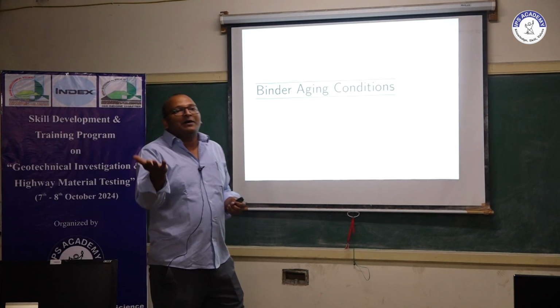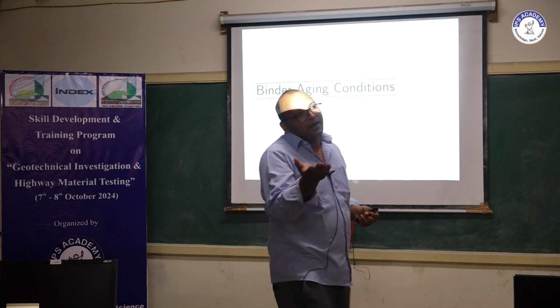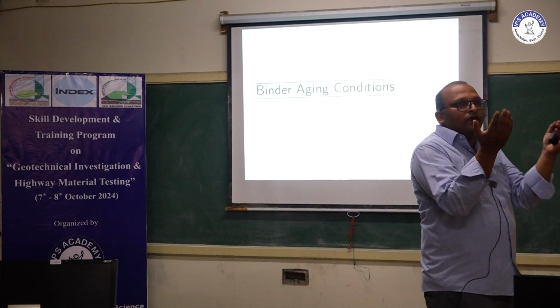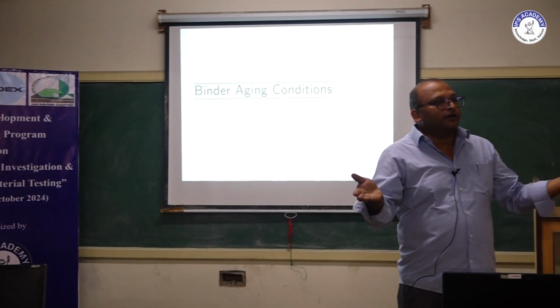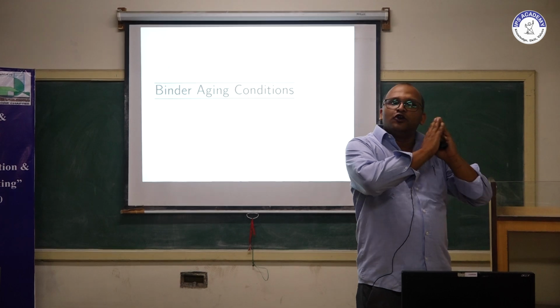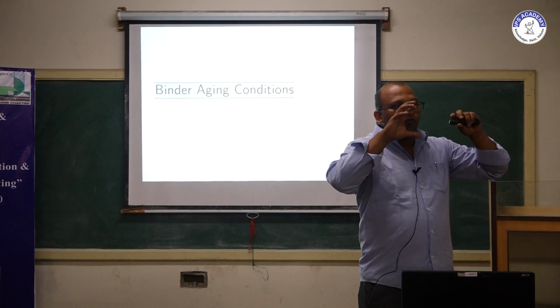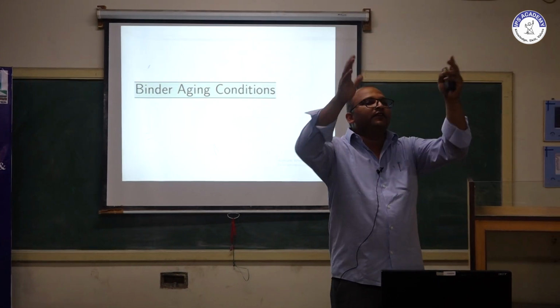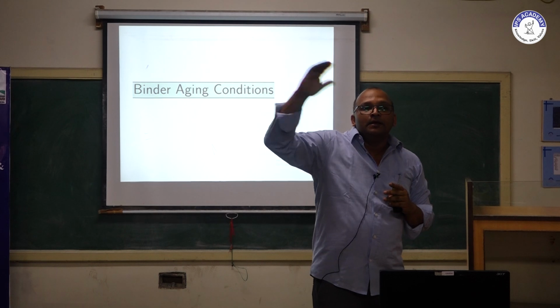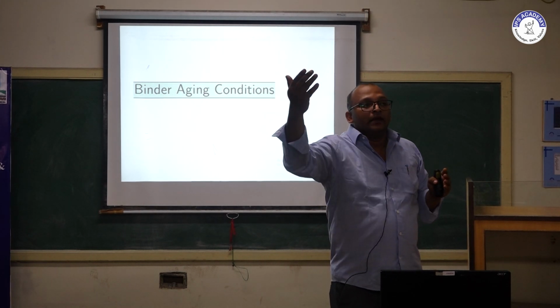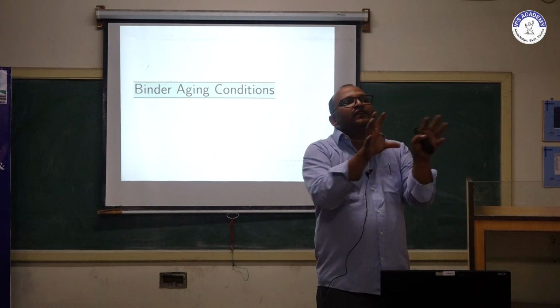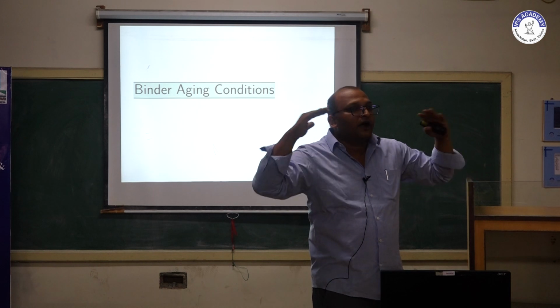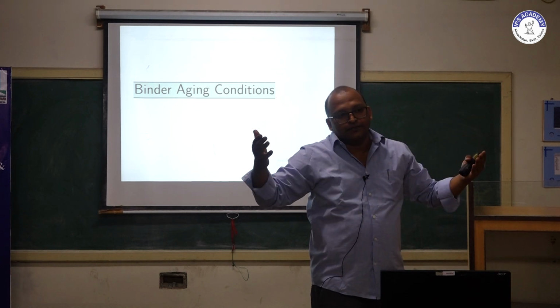Now let's discuss some other conditions which our binder undergoes. When you get your neat binder from the refinery, the binder will have no aging. But when you heat your binder to 135 or 160 degrees Celsius, the binder will undergo some aging. After this heating, you will mix it with aggregate. At that time also, the binder will remain at the elevated temperature.